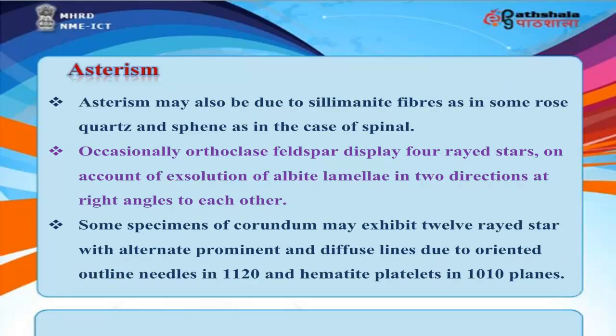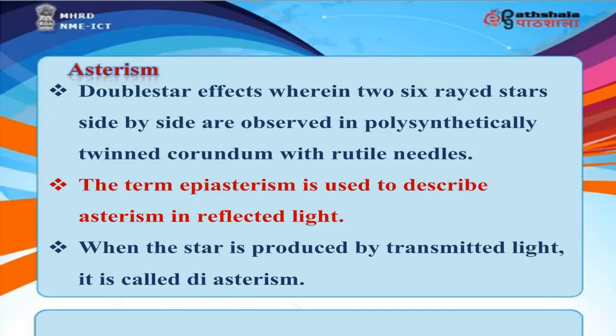Asterism may also be due to sillimanite fibers, as in some rose quartz, and sphene, as in the case of spinel. Occasionally, orthoclase feldspar displays four-rayed stars on account of exsolution of albite lamellae in two directions at right angles to each other. Some specimens of corundum may exhibit a 12-rayed star with alternate prominent and diffuse lines, due to oriented needles in 1120 and hematite platelets in 1010 planes. Double star effects, wherein two six-rayed stars are observed side by side, occur in polysynthetically twinned corundum with rutile needles.